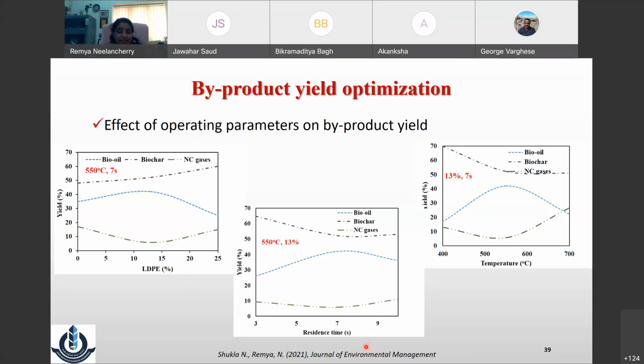So as you see, the residence time, that is the time for which our sample is kept at a predetermined temperature. That means at 550 degrees Celsius, we are keeping the sample. Again, you can see the time for which the sample is kept. It's only a few seconds compared to the minutes or hours in conventional heating, right? So at 550 degrees Celsius, even if you have 13% of plastic in your food waste, this is the yield with respect to residence time. So of course, there is a relative yield of each of these.